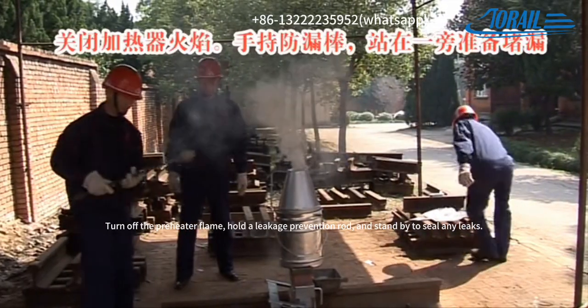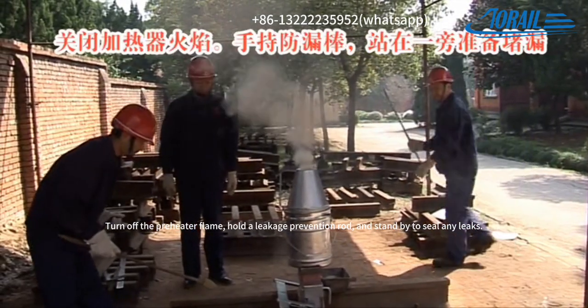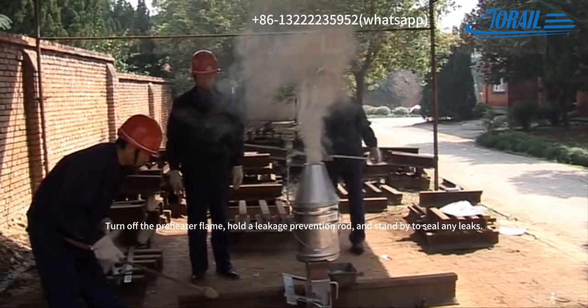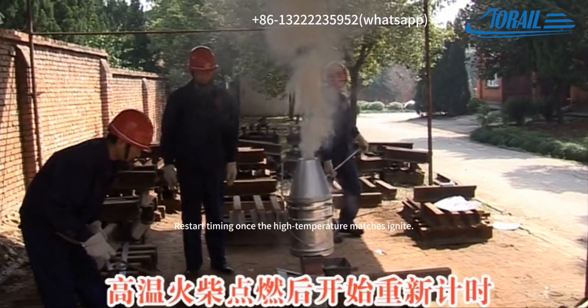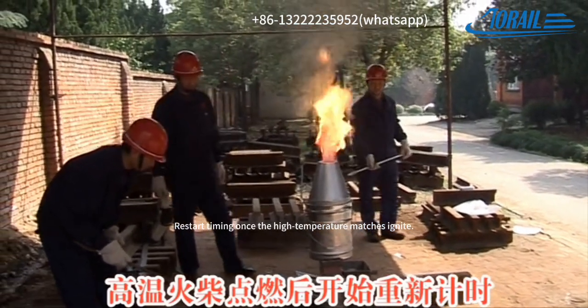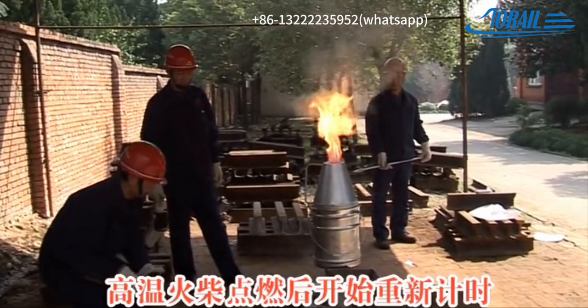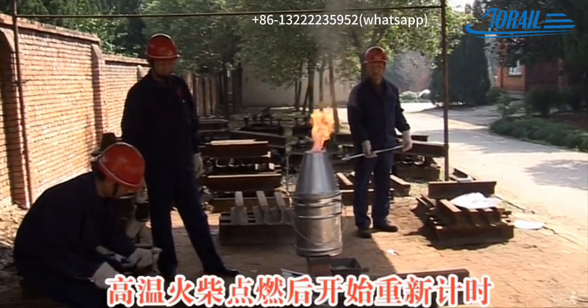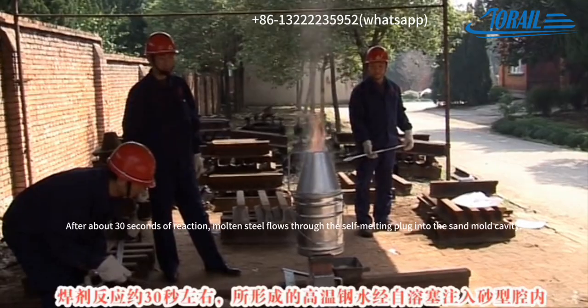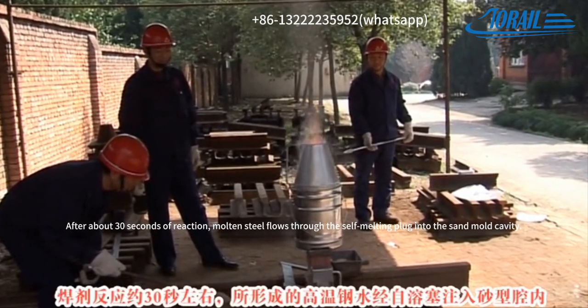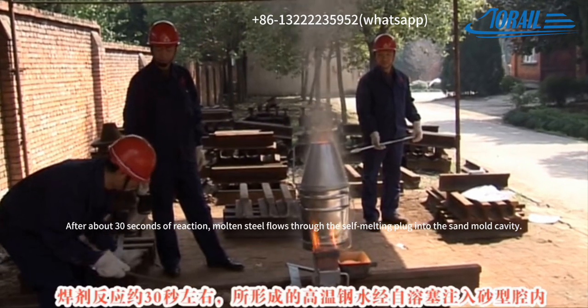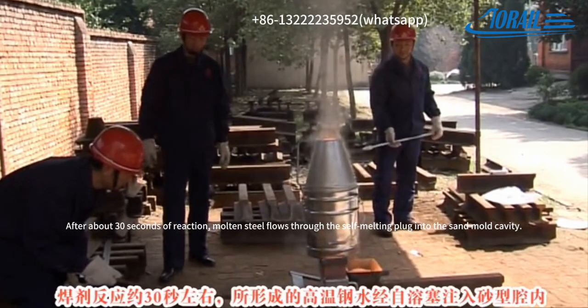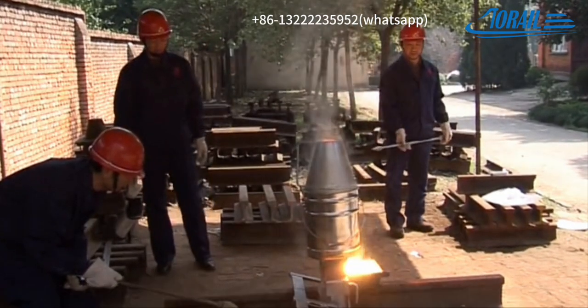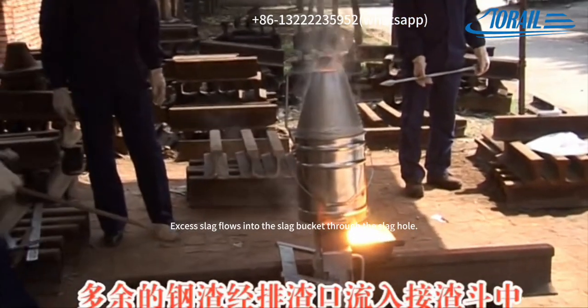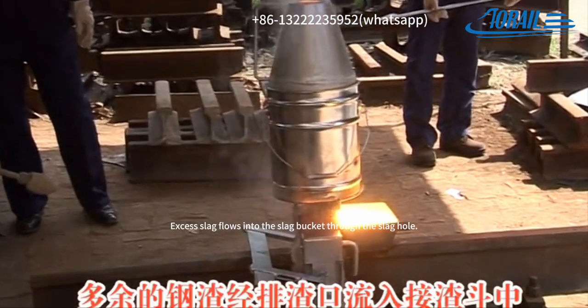Turn off the preheater flame, hold a leakage prevention rod, and stand by to seal any leaks. Restart timing once the high temperature matches ignite. After about 30 seconds of reaction, molten steel flows through the self-melting plug into the sand mold cavity. Excess slag flows into the slag bucket through the slag hole.